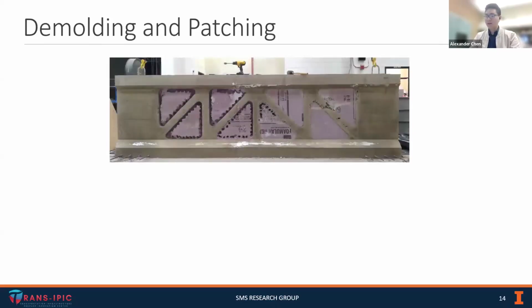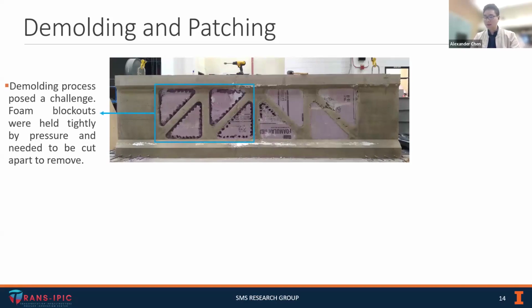Now, once the concrete hardened, we could begin demolding the specimen. This proved to have its own challenges because the foam was actually very, very tightly squeezed by the concrete. And so you can see in this image, in order to get the foam out, we had to chip it bit by bit away from the concrete.